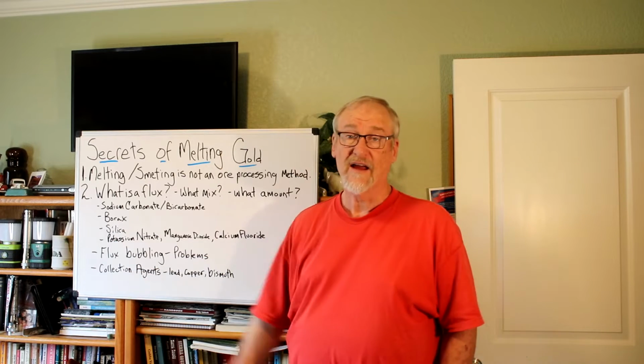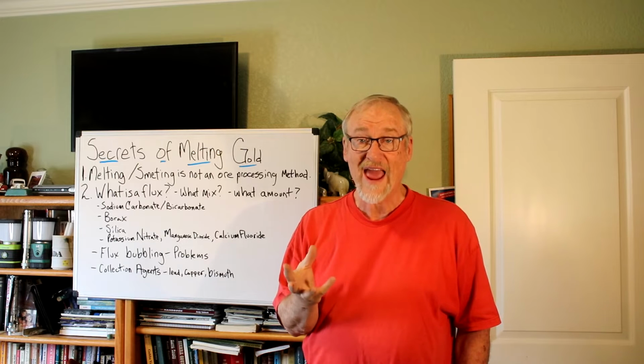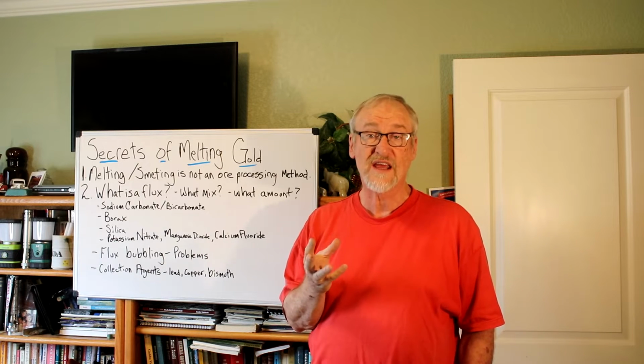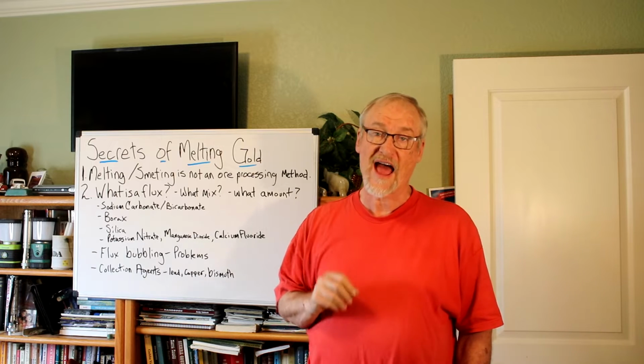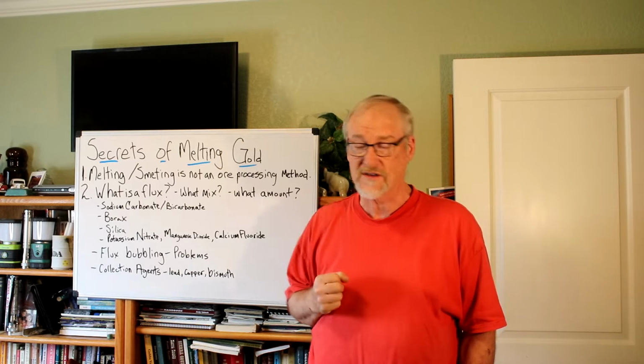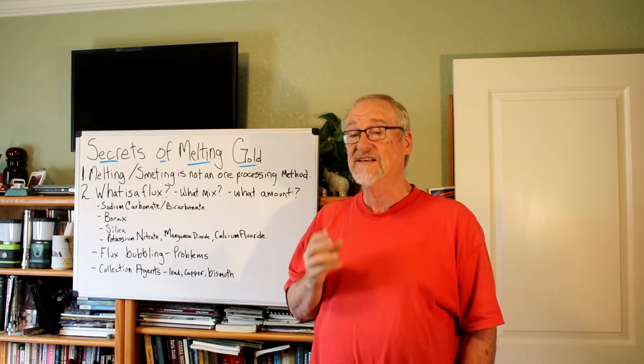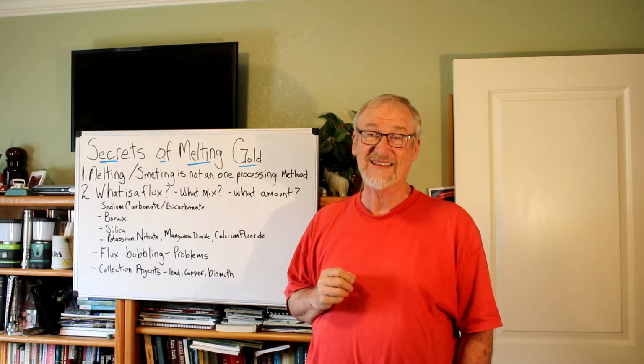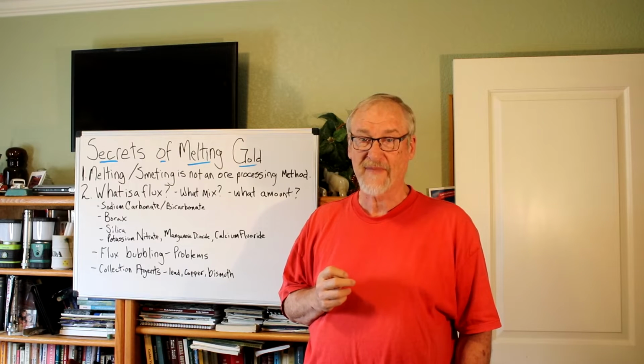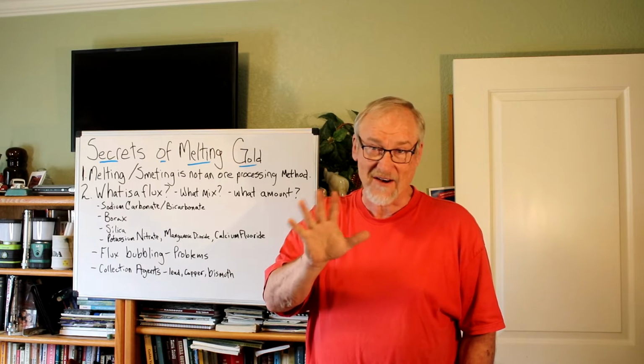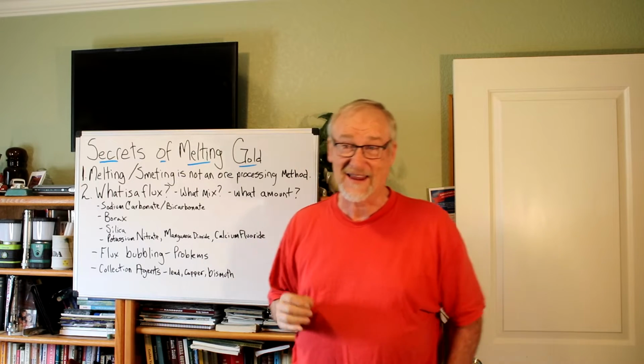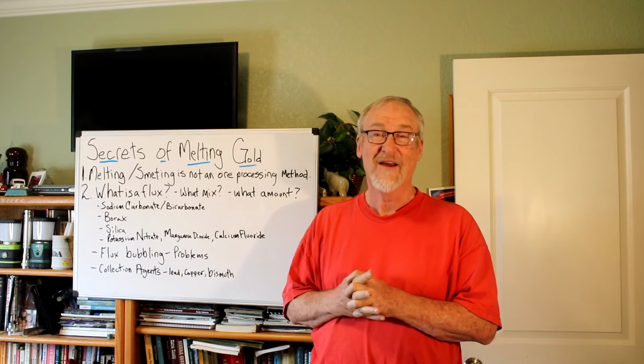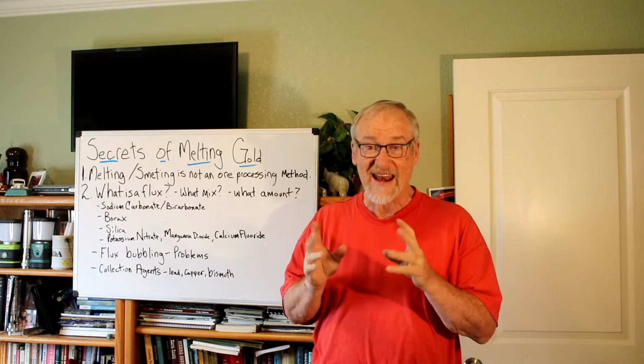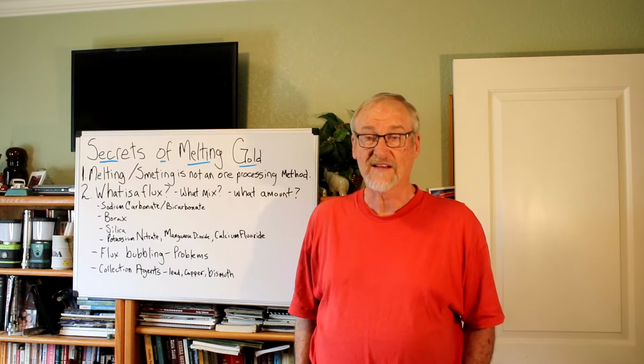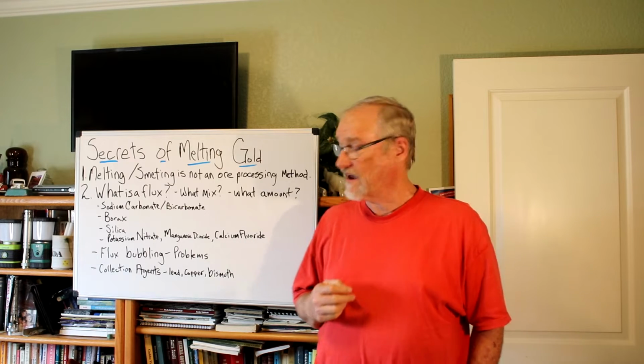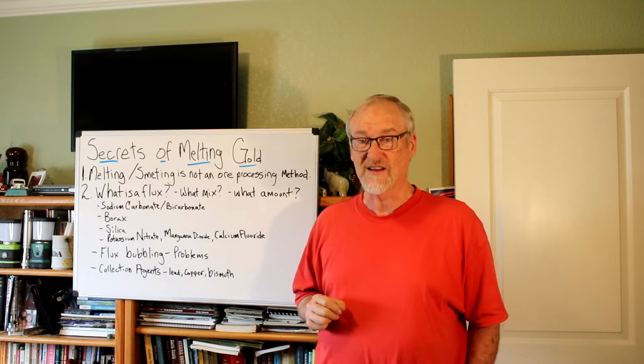All right, silica. If you have ores that don't have very much quartz in them naturally, then you want to add some silica. Silica is quartz. You want to add some very fine quartz. Sometimes I use broken pieces of glass. I use old antique glass that's already shattered. It's not like I'm taking a good piece of antique glassware that's valuable as an antique. I'm taking broken shards and that kind of stuff and adding a little bit of that as part of my flux. And that provides the silica if it isn't already there in your concentrates.